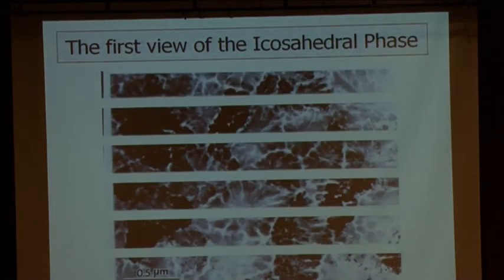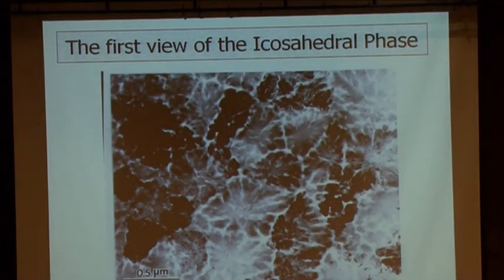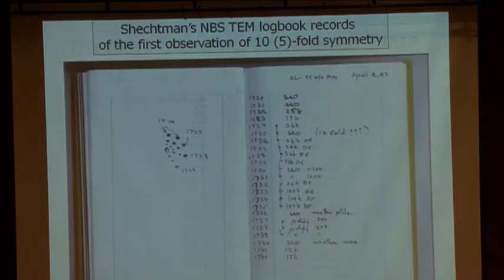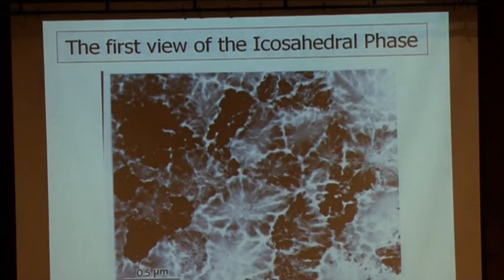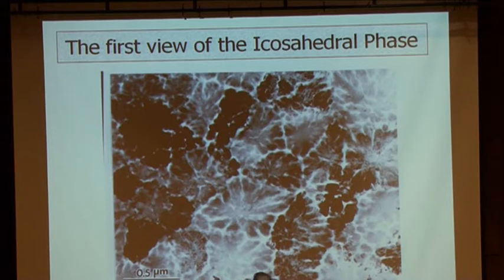And the picture of that, I'm going back here. You see, look at plate number 1724. This is the plate with a magnification of 36K. That means 36,000 times the magnification of the microscope. And this is how the picture looked like. What was strange about this is that, as you will see, for instance, here, there are several crystals, grains, here and here and here, that are pitch black, very black.